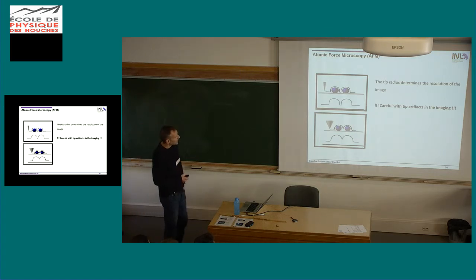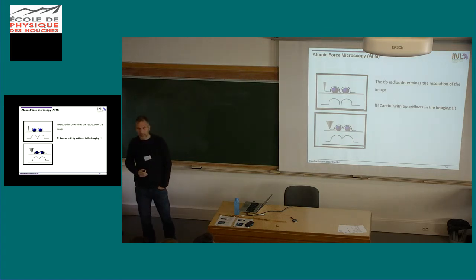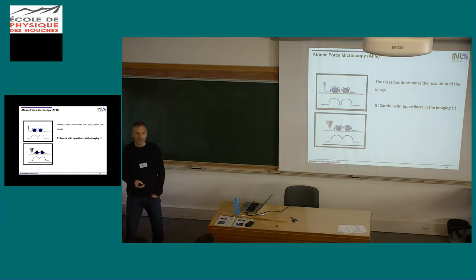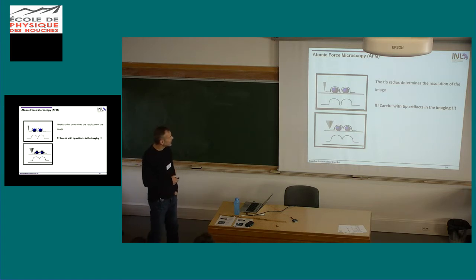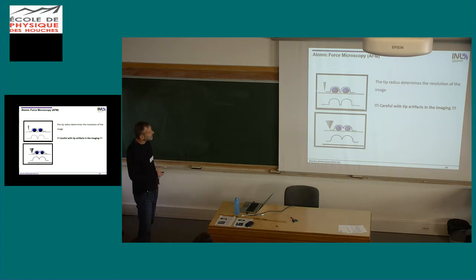So one general warning, as in all methods, whatever you characterize, there are always a lot of artifacts, there are always a lot of limitations, so always be aware that what you see is not always what you have. In AFM, this is nicely illustrated here. If you have two nanoparticles sitting on your surface, and you have a nicely sharp tip, you can actually measure this. Still, you don't know if this nanoparticle is a sphere. You just get this kind of thing. So you still don't know how your surface actually looks.